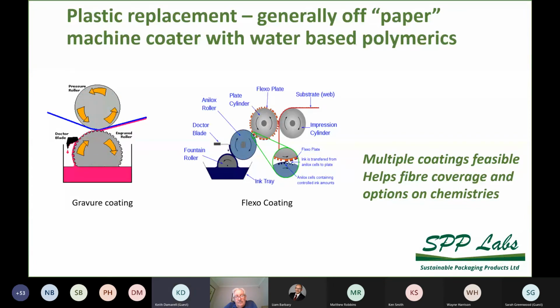The benefit of the multi-layer coating is that you can obviously build coat weight to ensure you're not having pinholes, which is very useful. But the other benefit is you can change the coating chemistries. You can have a couple of coatings with one chemistry that gives certain barrier functionality, but maybe by itself would have other challenges in terms of tackiness or blocking. And then you can put additional coatings on top of that that don't have stickiness or blocking. So you can actually choose different chemistries to build up the overall performance you're looking for. So whichever method is used, whether it's the blade or rod or curtain coating, or in fact the press applied coatings, there is still a critical issue to manage, and that is drying.